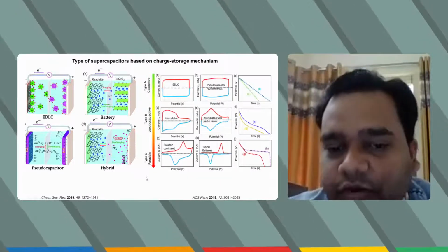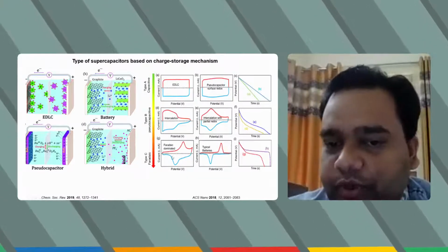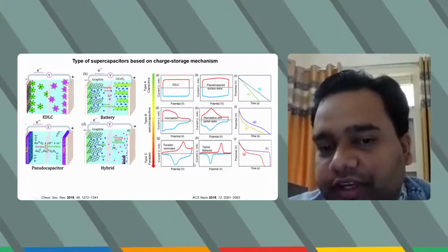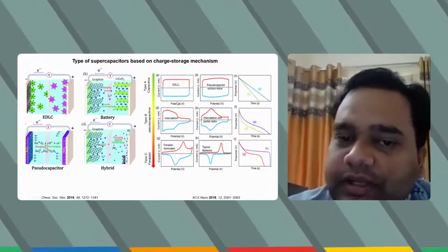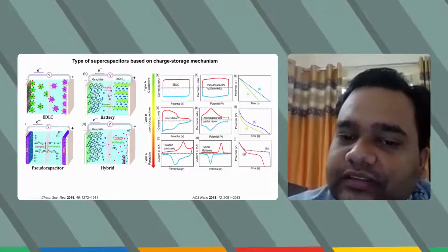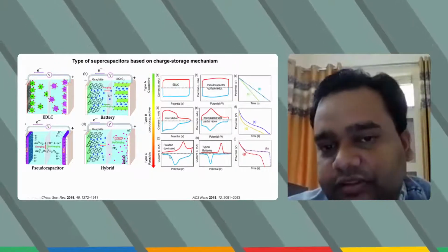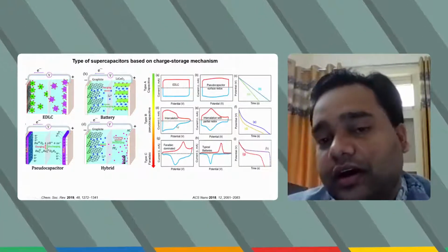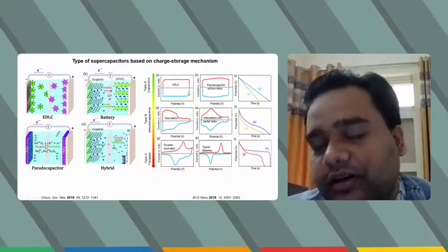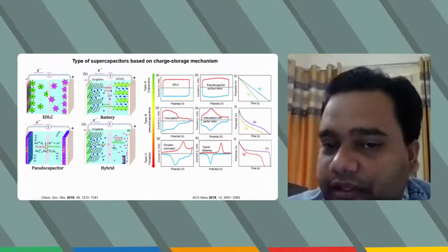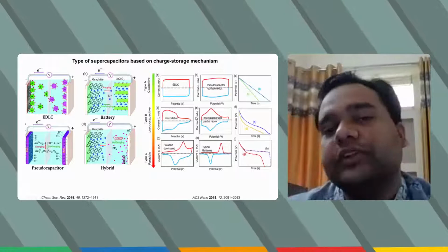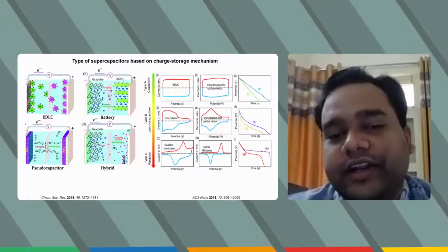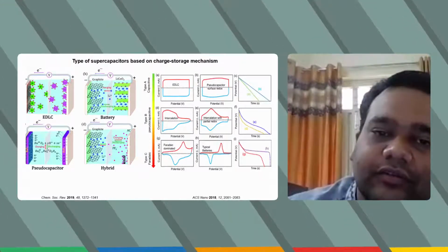Whereas in this Faradaic phenomenon, which is typical of batteries, you get this peak shaped CV. And in a pseudocapacitor, it is somewhat between the situation of EDLC and the battery system. So you don't get an ideal peak shaped CV, and it is neither rectangular nor peak shaped. It is somewhere in between EDLC and Faradaic. So based on this, they have different materials.